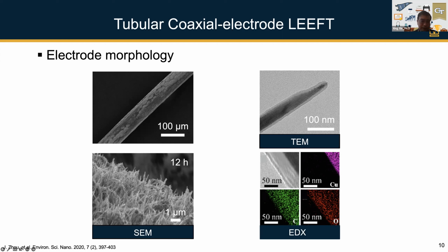You use different methods, you can also quantify the exact thickness of this polydopamine coating. Basically, we optimize this coating thickness, trying to balance the performance and also the synthesis time. If the coating layer is too thick, it will be very stable. You cover the surface, the electrode will be very stable, last for a very long time. But this is the electric field treatment, so the dopamine coating is actually not conducting.